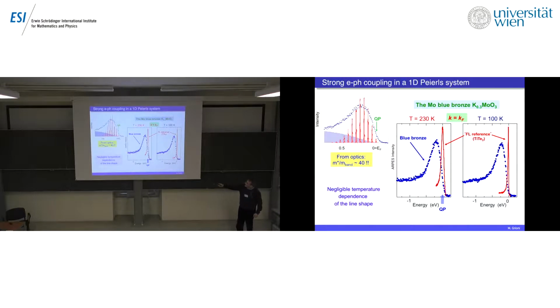And you can see what happens here when the temperature is changed from high temperature to lower temperature. So the red curve is for a good Fermi liquid. And as we saw before, the width of the quasi-particle peak is clearly reduced at lower temperature, while the spectrum of this Peierls system is essentially unaffected. And what we believe is that what one sees is essentially an almost totally incoherent spectral function. The quasi-particle peak is very small, is here, and most of the observed spectral function is incoherent, from this satellite, which cannot be resolved. And indeed, there is indication from optics that in this material, the mass is strongly enhanced.